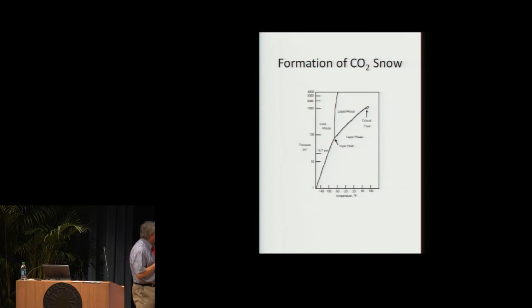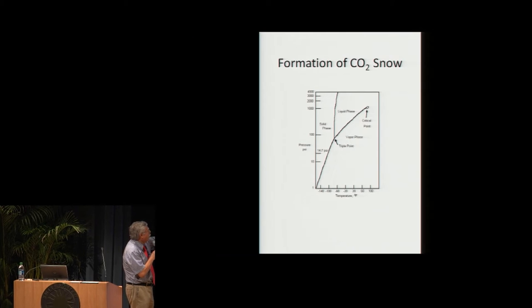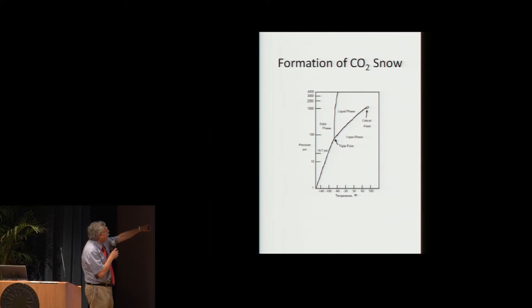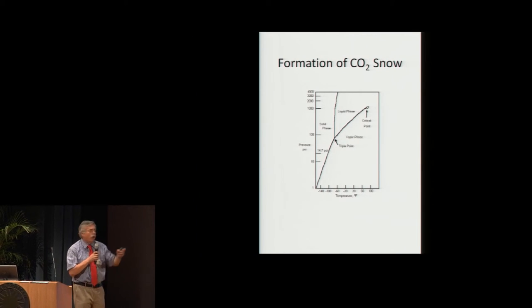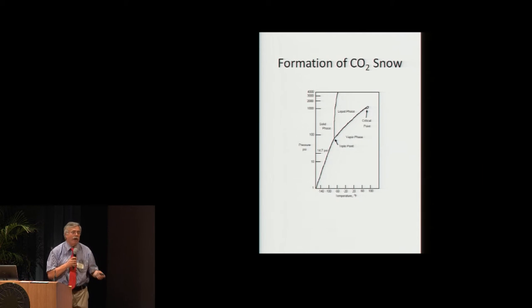When you start with a carbon dioxide cylinder, you're starting roughly at 800 psi at room temperature below the critical point. So you're on that line between the vapor and the liquid. At the end of the day, you're at 14.7 psi at room temperature. How you get there forming dry ice is not clear from the phase diagram. This is an equilibrium phase diagram, and this is not an equilibrium process.